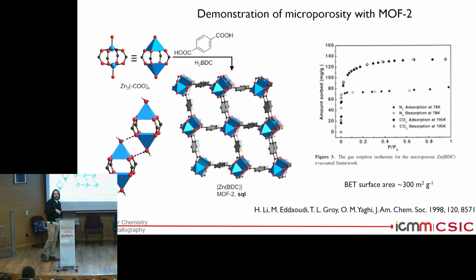And typically here what you do, and this is a gold standard to characterize porous materials, is what you do with any porous material. You take it to very low pressure, high vacuum, and then you start dosing small amounts of gases, like nitrogen at 77 Kelvin, behaving like a liquid, and then you see how the different amounts of gas are taken up by your porous material. With that, based on the shape of the isotherm and based on the amount, you can describe your material as being microporous, mesoporous, macroporous, and also importantly, you can quantify the surface area.